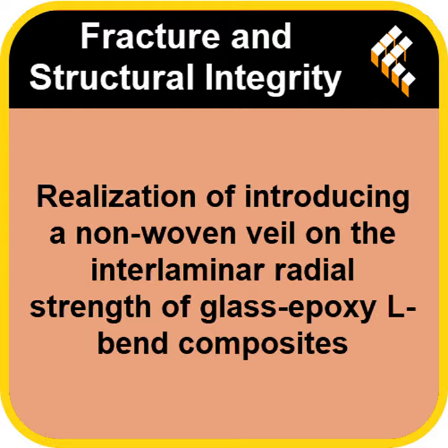And critically, the fibers, both the glass from the main layers and the carbon from the veil, looked really well embedded within the matrix. It looked like one solid, cohesive unit failed together. A tough break, literally. It confirms that tortuous crack path idea. Exactly. Now what about the ones that performed poorly? The higher density carbon veils, 20 and especially 30 g/m². What did their failure surfaces show?